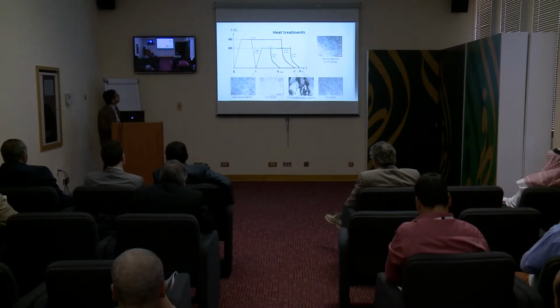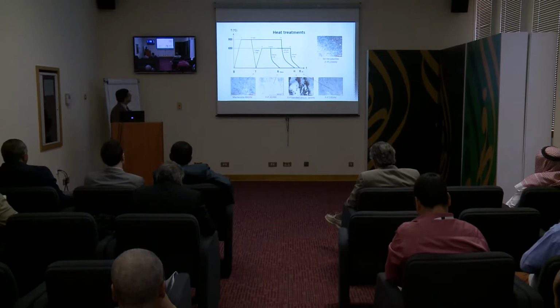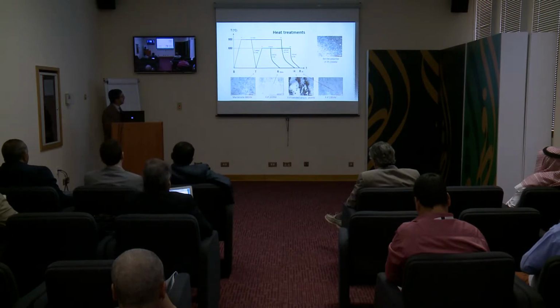Here are the different treatments. So you have homogenizing at 950 degrees, quenching after 30 minutes to have this microstructure, which is martensite with the biggest hardness compared to the as received one. And the second type of treatment is a longer homogenizing, which leads to this microstructure, a banded structure constituted of ferrite and pearlite.